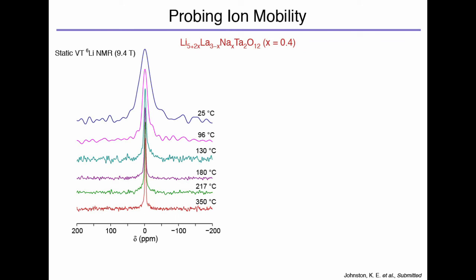So again, remember, these materials we're wanting to increase the ionic conductivity. So the first thing we want to do with the lithium is see if those ions are actually moving. We can do this using some variable temperature lithium NMR, and again, we want to do this over a much larger temperature range to see how much that lithium can move. We can see that at room temperature, the line is very, very broad, but as we increase the temperature, it gets very, very narrow, indicating that the lithium is, in fact, moving within this material.